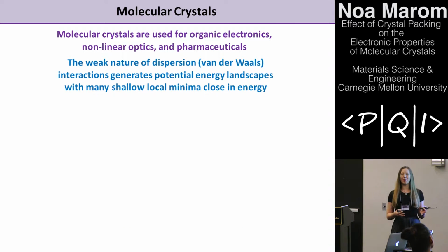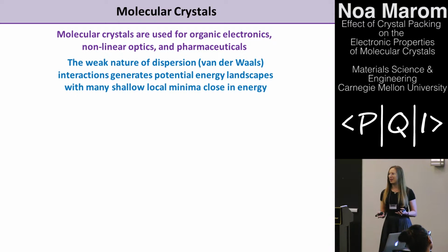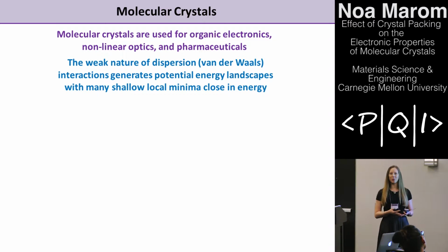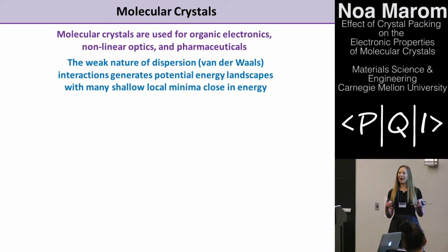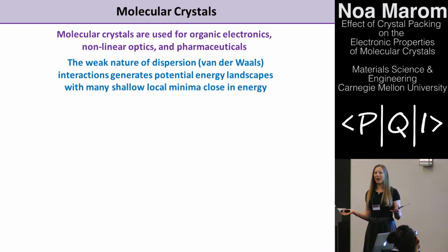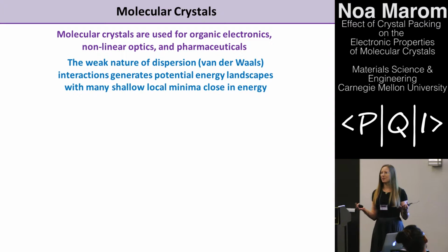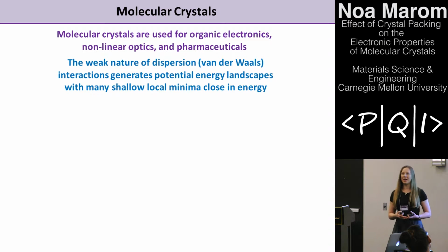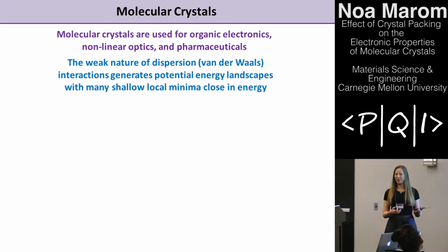Molecular crystals are used in applications in pharmaceuticals and in nonlinear optics, and also in organic electronics. And the thing is that the weak nature of van der Waals interactions produces potential energy surfaces that are very shallow, and they have lots and lots of energy minima that are very close in energy.